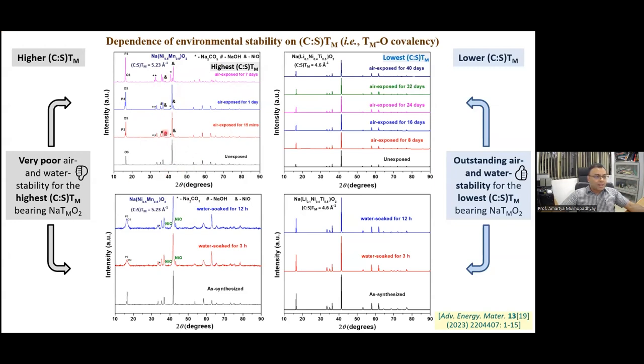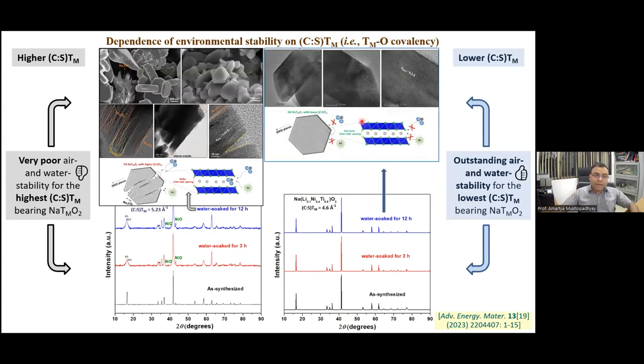We can see that this material starts degrading in terms of composition as well as structure, whereas this material having the lowest charge to size ratio in the transition metal slab is stable even upon up to 40 days of air exposure. Even when soaked in water, this material is absolutely stable and no change can be seen in the structure, which proves that this material is highly water stable, not just air stable, and that goes as per our hypothesis.